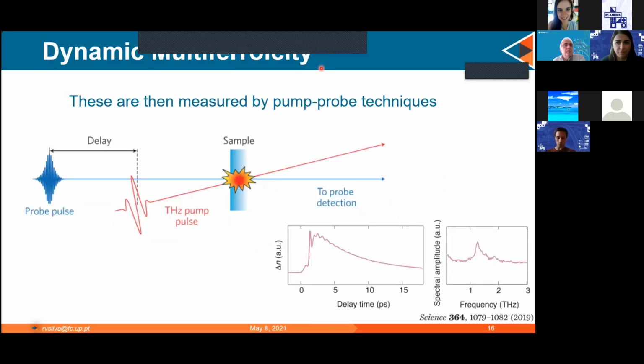So this was already tried very recently in 2019, and they tried only the ferroelectric part, which is the easiest, and they used a terahertz pump pulse to induce the motion of the atoms in a sample. And then what you do is you send another pulse, which is the probe, and you have some delay. And this probe can show if it's ferroelectric using second harmonic generation technique, or if it's ferromagnetic using magneto-optic Kerr effect.